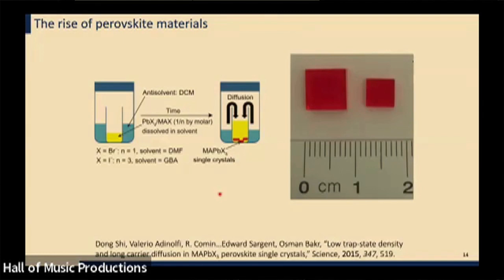And we studied this using some really basic materials growth and photophysics. It's actually the kind of stuff you might have seen at Bell Labs in the 1960s and the 1970s, where we were growing single crystals of these semiconductors in the liquid phase and using classical spectroscopies to study how clean their band gaps were, and got results that even though these materials were being made around room temperature, in an open lab, in these single crystals, the trap state density was in the same ballpark as in the semiconductors that we make in clean rooms at high temperatures with incredible purity of processing.